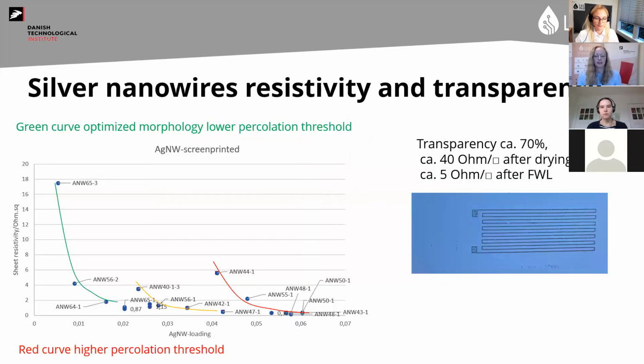So here we have an example of some different synthesis we did. In the graph, all these A and W numbers are different synthesis we performed with different morphologies. And what is key here is to see we want to have a low loading of silver nanowires because then it's more transparent. But we also still want a low sheet resistance. So we need to find the optimum here. And if you look at the red curve, it has a higher percolation threshold, while the green one has a lower percolation threshold.